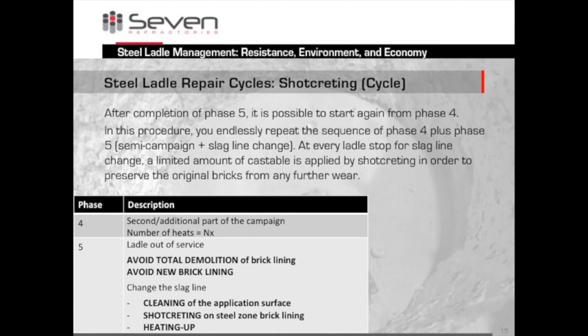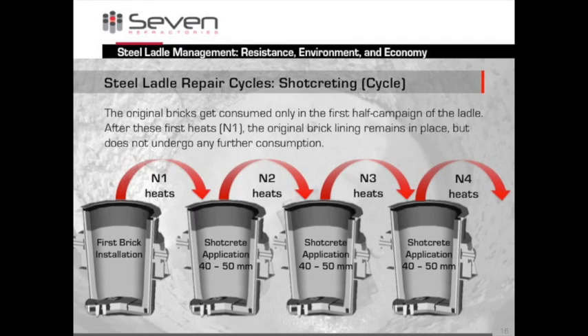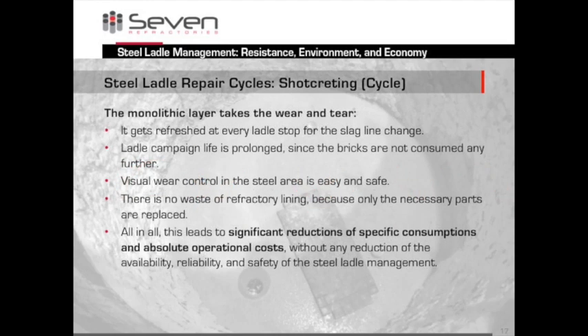In principle, you can repeat this phase forever and ever: take the ladle out of operation, shotcrete what is needed, and heat up again. This also works to protect the existing brick structure. A very typical application in practice: after the first brick installation and heating runs, a shotcrete application of 40 to 50 millimeters is applied between each run — potentially going on forever. You make the monolithic protection layer do the work, check where you need to repair, apply shotcreting there, and use minimal material. The cost reduction is obvious and there is no compromise on safety or reliability.